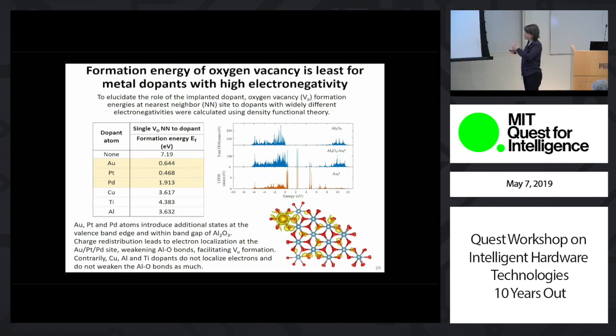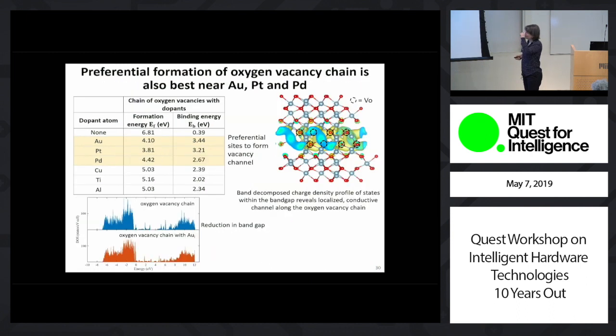So that's based on the effect of single ion in the creation of a single vacancy. But these conducting filaments must have many vacancies. And we have simulated that scenario by placing a few dopant atoms and several oxygen vacancies around them, and have also compared the formation energy and binding energy of that vacancy channel to the implanted dopant atoms.